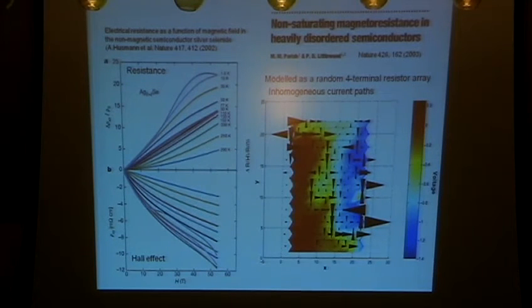What's actually happening in your sample is that these are the current contacts. These arrows are the current paths. The greens are the voltages. What, of course, happens is that at low fields, the current follows the path of least resistance. At high fields, the current follows the path of greatest resistance. Because if there's an electric field line, and then you're in a magnetic field, and there's a Hall effect, the current will always go at an angle to the electric field. And so the current then takes a winding path, avoiding all of the low resistance pieces of the material. And so here's that path, and the voltage drop taking the sum from one corner to the other. And most of the time when you put your contacts down to measure the longitudinal magnetoresistance, you'll be on either side of this current path and you'll get this effect.